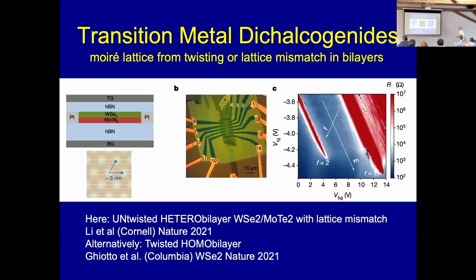What's really remarkable in this system is that they can be tuned to a large degree using gates. So here is an example of this heterobilayer experiment at Cornell, in which we have this tungsten diselenide molybdenum ditelluride, which is in a matrix of boron nitride, and there is a top gate and a bottom gate. That's a simplified, of course, picture of this more complex device. And by controlling separately the two gates, you can actually move. So this is a map of the resistance measured as a function of bottom gate and top gate. And you see that you can actually move in this phase diagram.